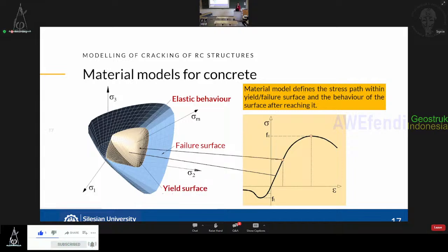Then when it reaches the plasticity limit, it means that such a point is exactly on the yield surface. And then by the definition of the flow rule, we would know how such a yield surface would behave. For concrete, we usually use the isotropic flow rule, which means that we can imagine that such a yield surface would be swelling with a specific rate until it coincides with the failure surface. So this is this ascending branch.